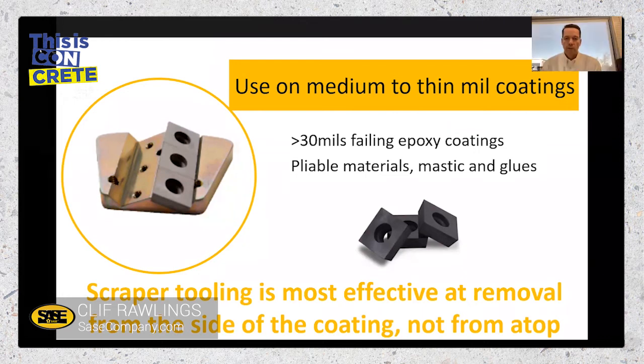Yeah, and I would say for the most part, they just will not cut into concrete. We went into places where the cure and seal has been put down very poorly. This is a great way to get the floor to an even starting point, because if we go over a wave of cure and seal with a hybrid or a metal, you're going to cut concrete on one side and you're going to be cutting coating on the other. Yes, eventually you get it all gone, but you got an uneven cut. This is a great way to get an even starting place so that you're relatively flat. Knock those waves down to make your next cut look better too.